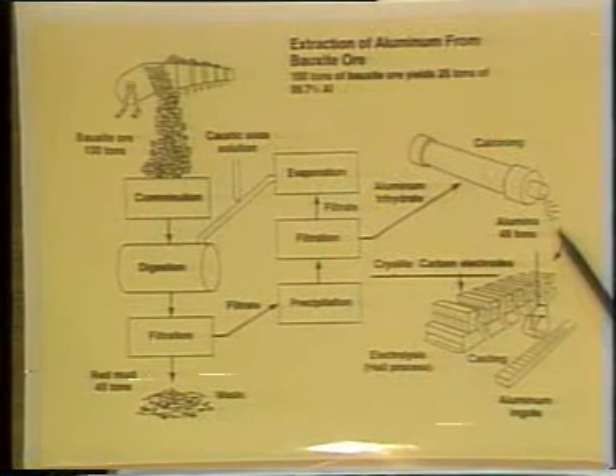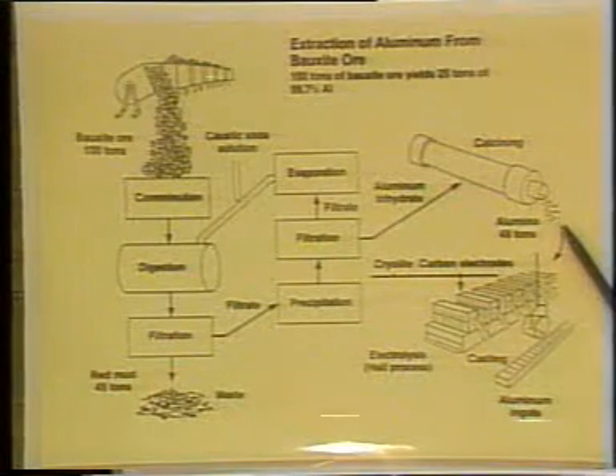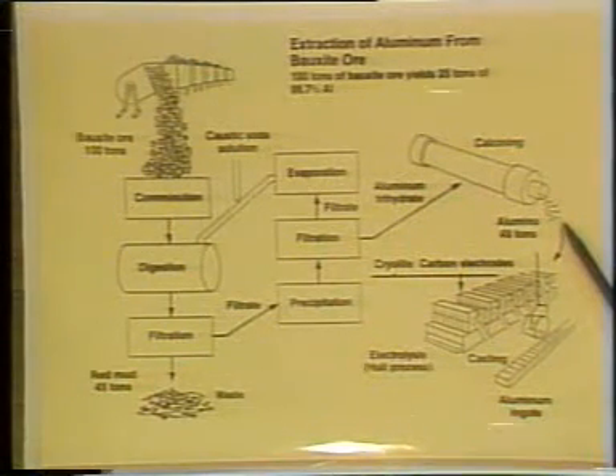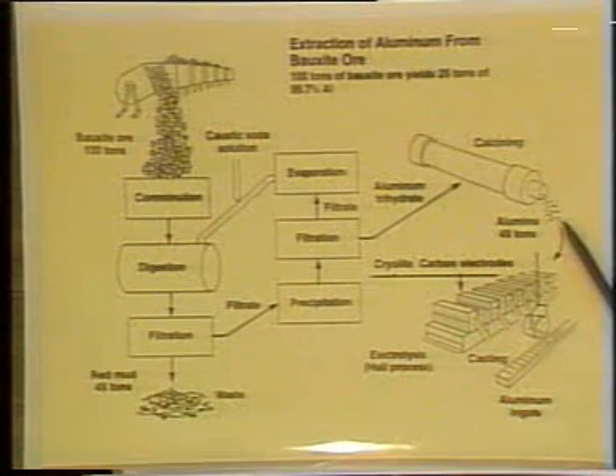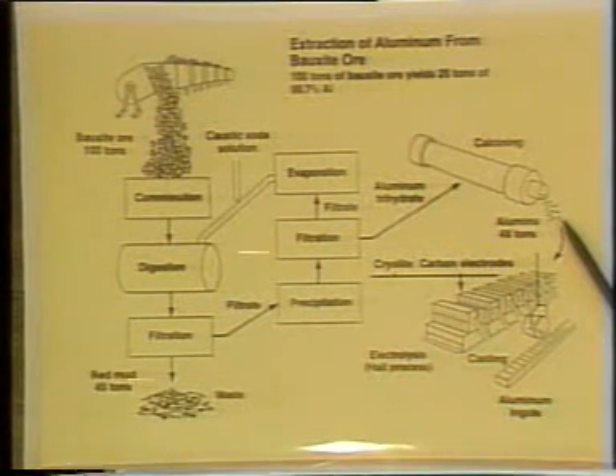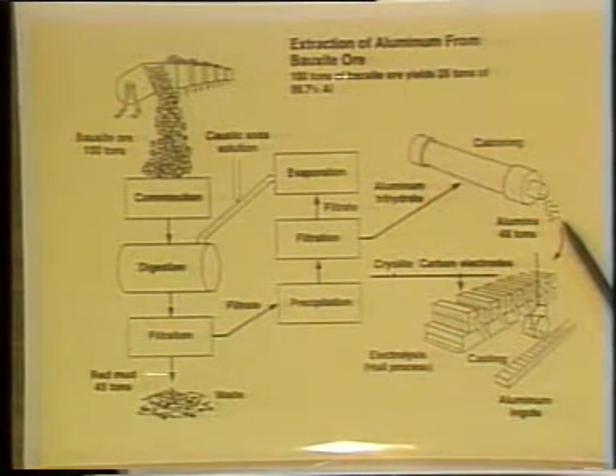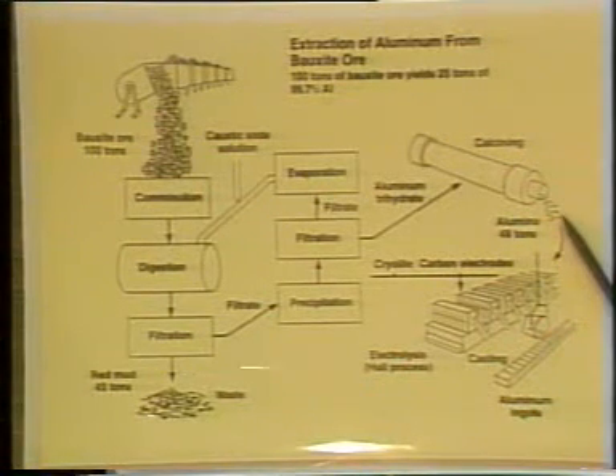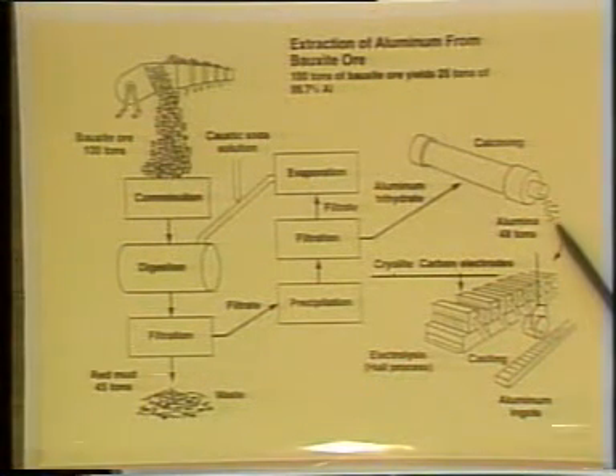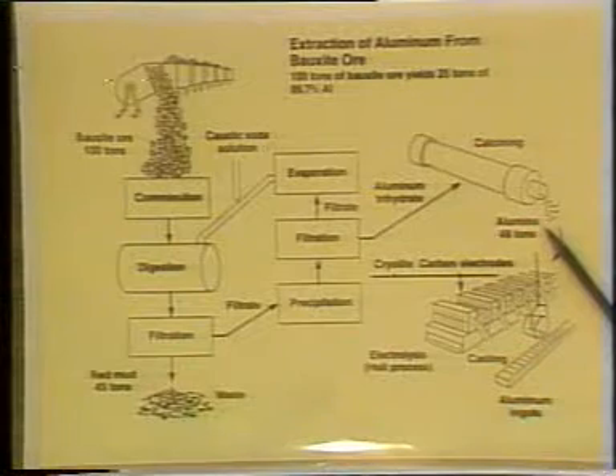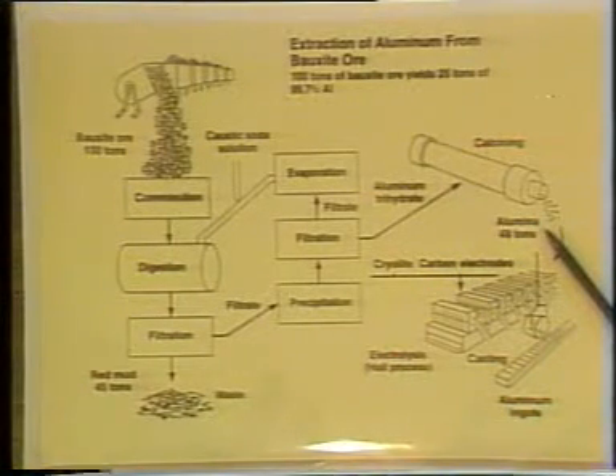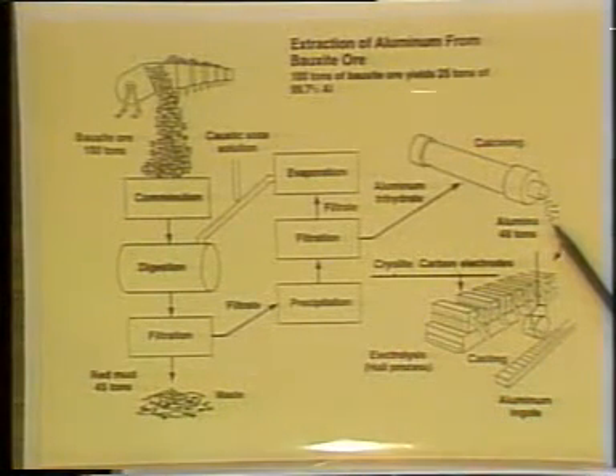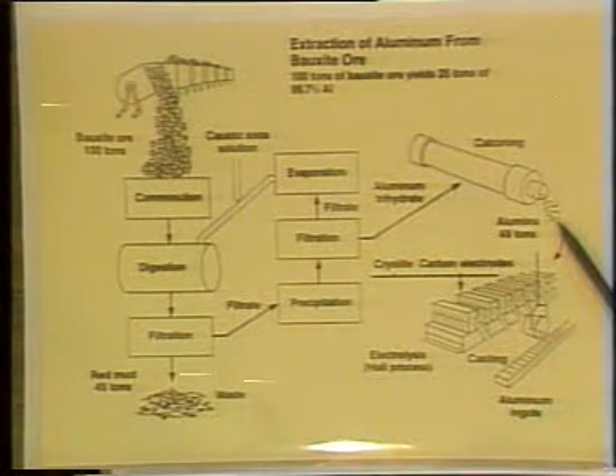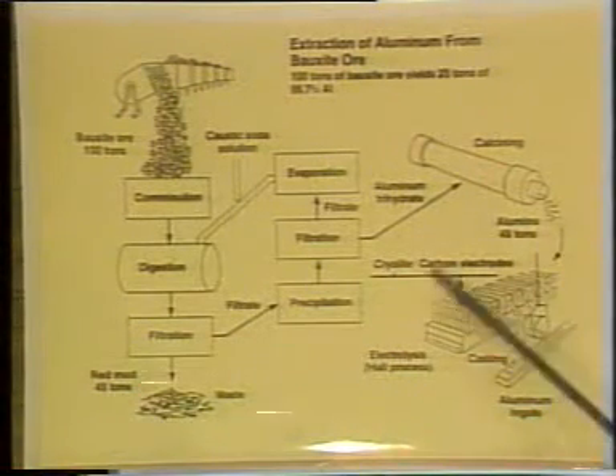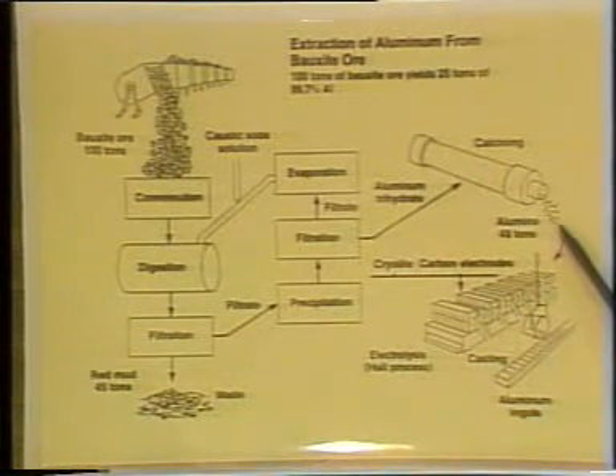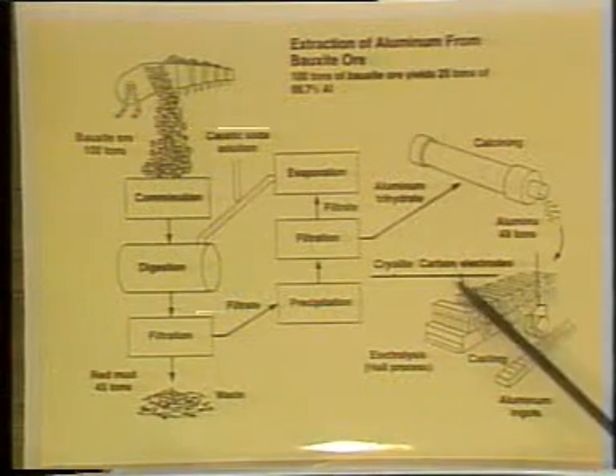And all Charles Hall did was to find out, well, he knew beforehand that he couldn't melt this aluminum oxide. Its melting point is very, very high. If he gets it molten, he can't just electrolyze the aluminum out of it. So what he found out was, if he uses cryolite, that's a sodium aluminum fluoride, a mineral that we can produce synthetically, but we find in nature. If he took this cryolite material and put the aluminum oxide in it, it would dissolve.